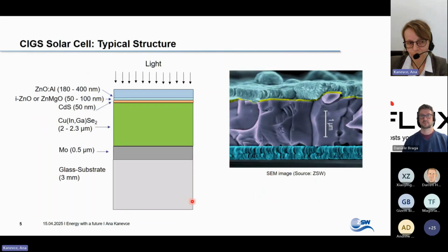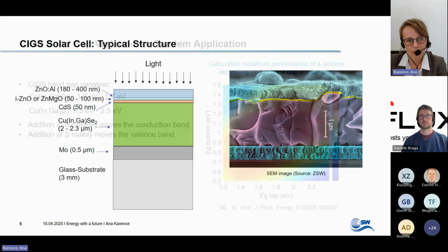Here is a typical structure. It's grown on glass substrate or on a foil. As a back contact, we use molybdenum. It's about half a micron thick. CIGS is 2 to 2.3 microns thick in our institute, and it's polycrystalline. Here you can see the SEM image. On the top of the absorber comes a buffer. Cadmium sulfide is a standardly used buffer. It's about 50 nanometers thick, and on the top of cadmium sulfide, there is another buffer layer. This is either intrinsic zinc oxide or zinc magnesium oxide, and those are 50 to 100 nanometers thick, and then a window layer is aluminum doped zinc oxide.